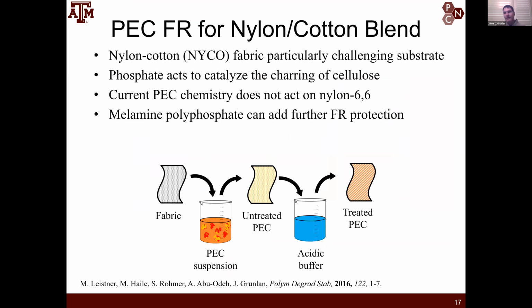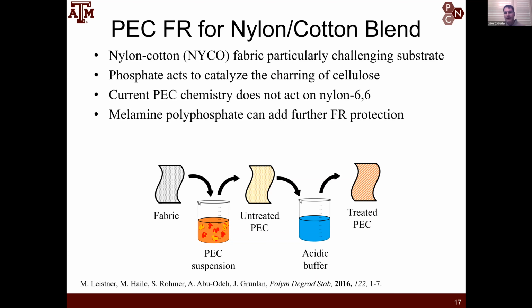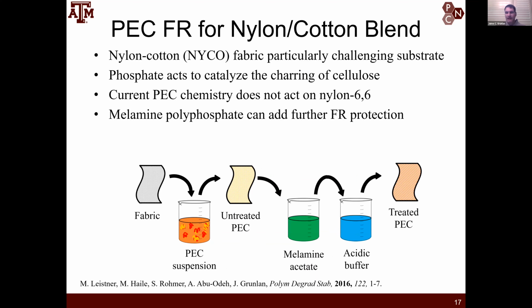Nylon and cotton, which a lot of clothing is usually a combination of polyester, nylon, and or cotton. So nylon cotton is very challenging to flame retard because cotton combusts, nylon melt drips and burns much hotter than cotton. So it's a bad combination in terms of fire, those two chemistries. So we had to modify our recipe. So we took a very similar polyelectrolyte complex. We still dipped it into the buffer, but before we did the buffer curing, we added a melamine solution so that we formed melamine polyphosphate in situ. It's a water-insoluble molecule, but we formed it in situ on the textile itself prior to complexing.